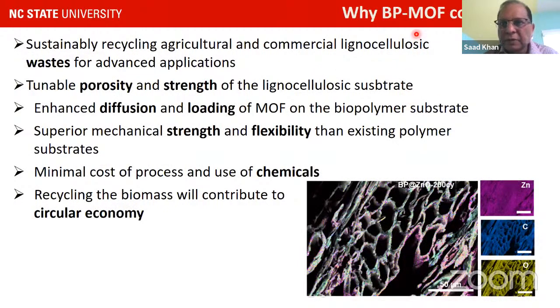So why banana paper MOF composites? Again, we are going into natural material which are used from waste, and these are lignocellulosics. We have tunable porosity and strength, and that presumably will help us get a higher loading of MOF, and easy diffusion of gases if you want to capture gases. These lignocellulosics seem to have good mechanical strength and flexibility, and then we would avoid using harsh chemicals, or not avoid, but probably use less of them. This is a picture of a banana paper where MOF has been deposited. I'm showing it ahead of time, and we have used a zinc-based MOF referred to as ZIF, and you can see in this cross section that the MOF is well in there, not only on the outside but inside as well. So there is a nice coverage of MOF in these banana paper composites.